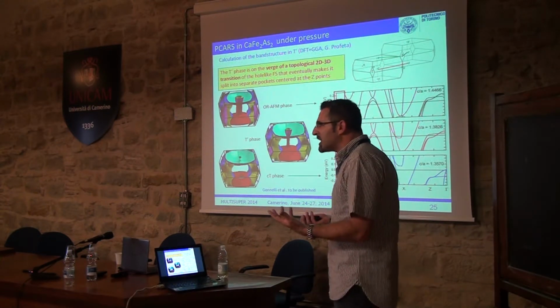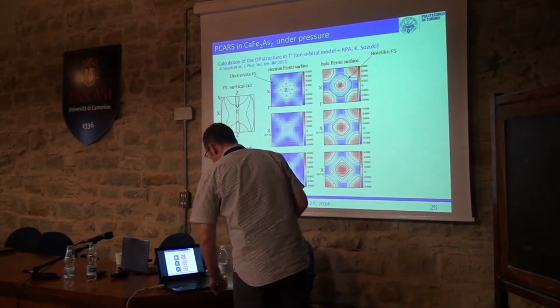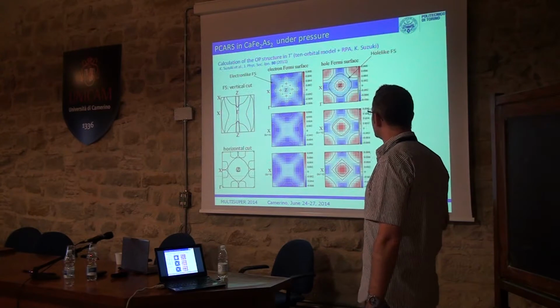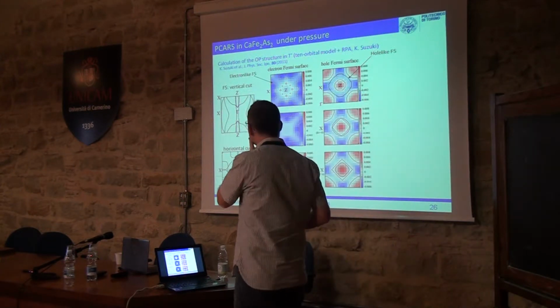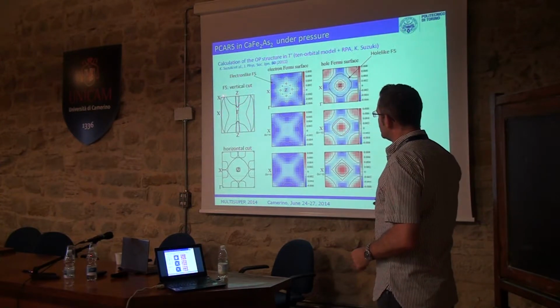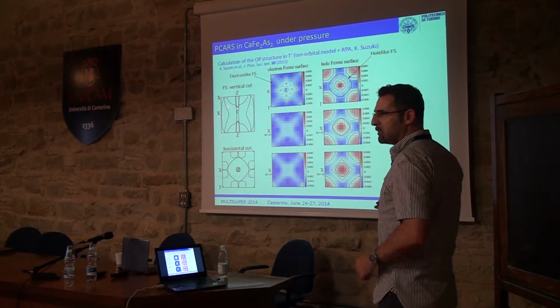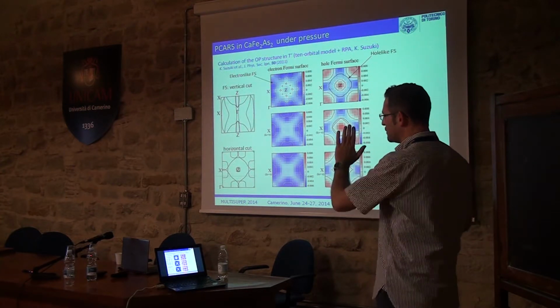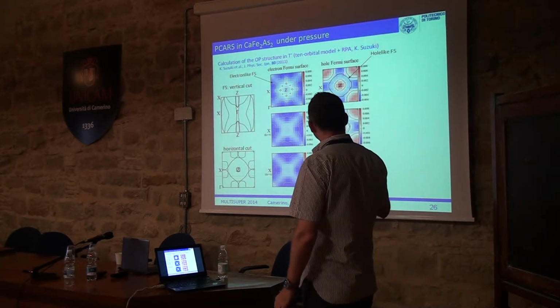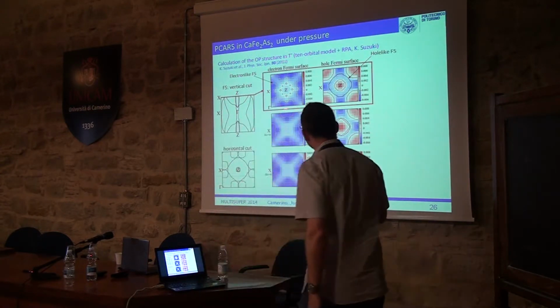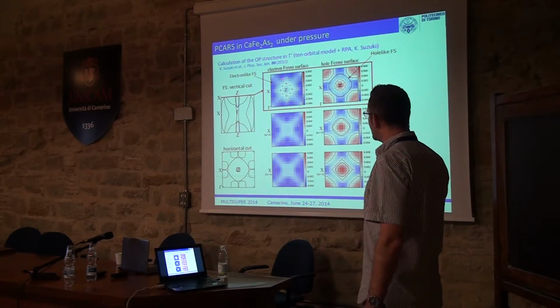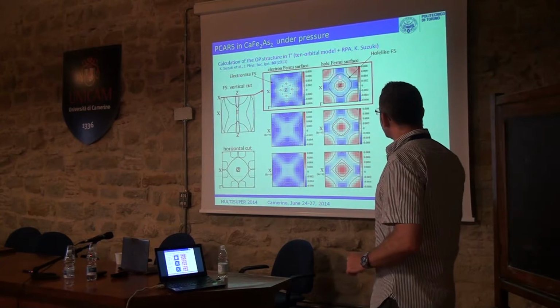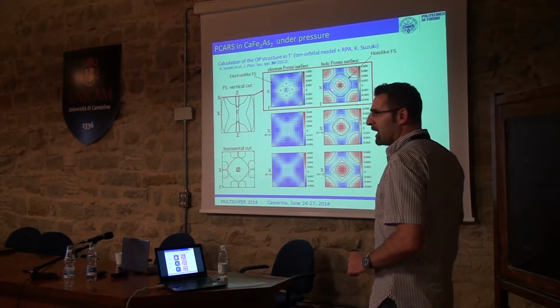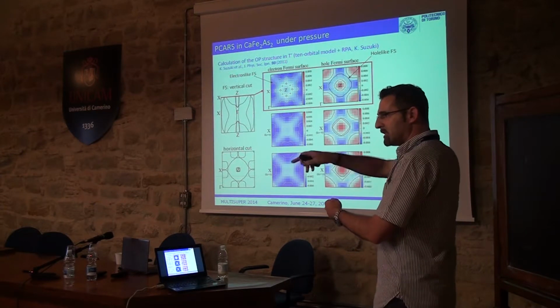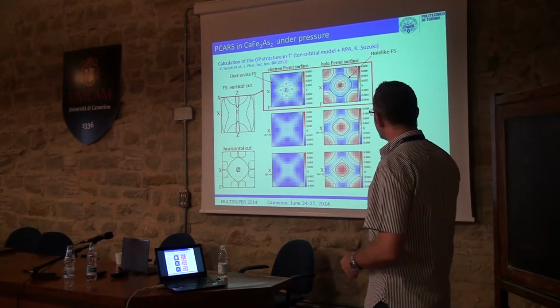So what is the expected structure of the gap? We asked Dr. Suzuki to perform calculations within the 10-orbital model plus random phase approximation. This is a vertical cut of the Fermi surface. These are the hole-like Fermi surfaces. These are electron-like. This is a horizontal cut. You see that these are the maps of the gaps. For example, here, on the top of the Brillouin zone, you see that the gap on the electron-like Fermi surface is almost isotropic. The black one is the hole-like Fermi surface profile. Here the gap has a fourfold oscillation, so it's anisotropic in the plane. But it has everywhere the same sign.